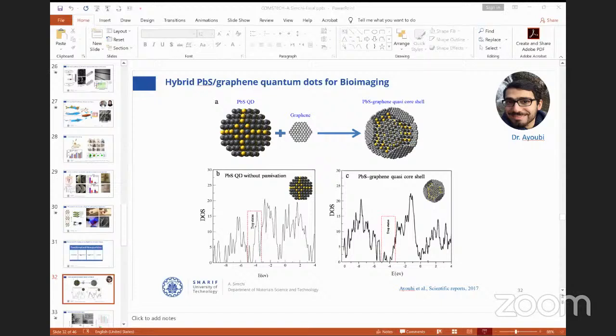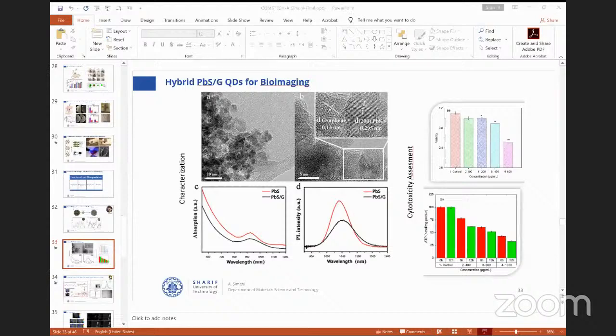My idea was whether it is possible to conformally coat PbS quantum dots with a layer of graphene without losing the PL. At first, as you see in the downside images, we used computer simulation, DFT simulation, and showed that it is possible to passivate the PbS quantum dots by a thin shell of graphene. And then we went to the laboratory and tried to make it. We developed a special procedure, which I'm not going into the details of, but I show you here in the TEM images that it is possible to have one layer of graphene conformally coated on PbS quantum dots.